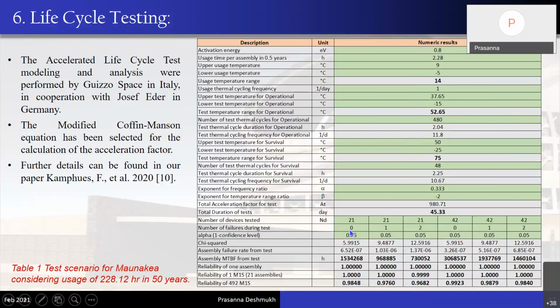you will be able to predict what is the reliability of the system if 0 actuators fail, if 1 actuator fails, if 2 actuators fail, and what will be the corresponding mean time before failure of a given system. So as you can see here, if we have a setup of 21 actuators, and if there are 2 failures, we get an operational life of 730,000 hours of mean time before failure for that warping harness mechanism. And similarly, when you increase the sample set, the overall mean time before failure will increase if you have the same number of failures.